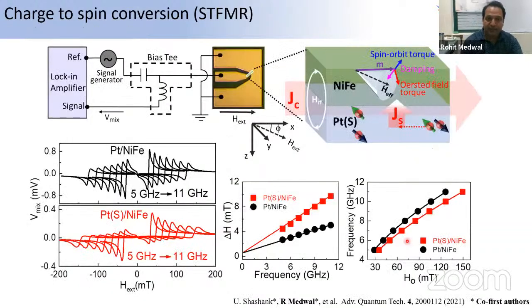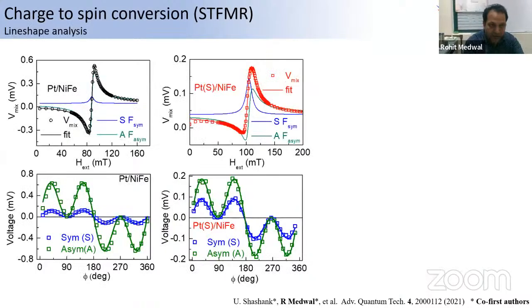After this, we made the devices out of it using the photolithography technique. And what we observe is the spectra which we record from the spin torque ferromagnetic resonance for the platinum and the PtS. Clearly, there is a shift in the symmetric and antisymmetric components. I can maybe draw a line for easy understanding. This is the shift I'm talking about. You can see that the relative shift is higher in the case of the PtS as compared to the pure Pt. So we deconvolute.